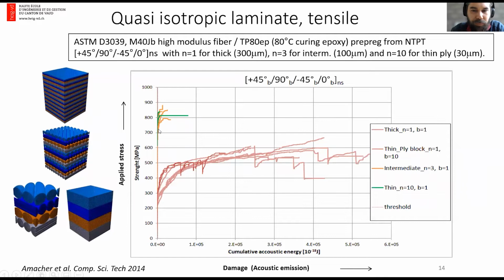While for intermediate ply thickness, 100 micrometer plies, or thin plies like 30 microns per ply, we can observe here that the onset of acoustic emission is much higher, more than twice the value of the onset for the thick ply. And we don't have much acoustic emission before failure. So this is exactly what we have observed in the videos, but seen from the acoustic emission standpoint.